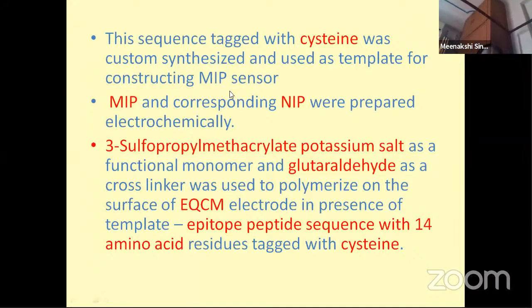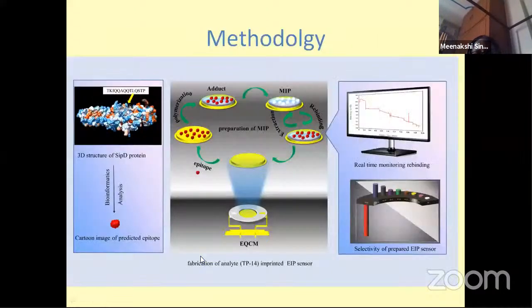So this is the molecularly imprinted polymer as well as the non-imprinted one. Non-imprinted means the polymeric matrix without the template. The functional monomer used was 3-sulfopropyl methacrylate potassium salt, and glutaraldehyde was used as a cross-linker to polymerize on the surface of the electrode in presence of the template. And this template was the epitope peptide sequence with 14 amino acid residues tagged with cysteine. And this 14 amino acid residue was predicted with the immunoinformatic tools.